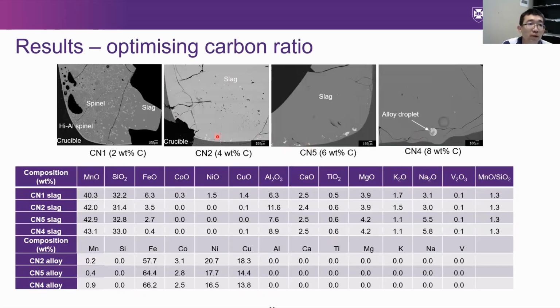So here is the result of optimizing the carbon ratio. By increasing the carbon addition, we first reduce the alloys and then leave the slag as a glass phase. So this is the alloy composition. Then we can get the iron, copper, nickel alloys, and from this slag we can indicate that almost all the copper, nickel, and cobalt oxide are fully reduced.